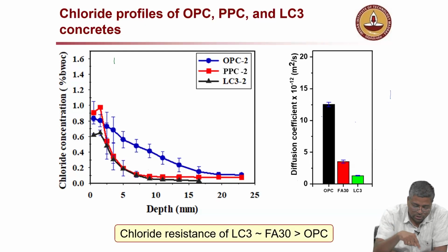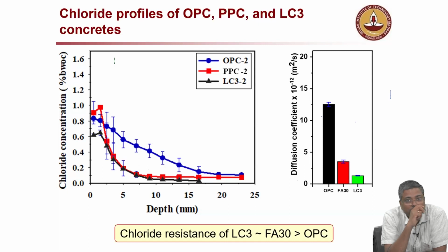Now you can see the slope. Now go through, let's say at 5 mm depth. Which concrete has more chloride in the first graph? Which one has more chloride in the 5 mm depth? OPC. That means what? Speed of penetration is more or less? More. 10 mm, same thing, right? If you look at 10 mm, in the case of PPC, not even a very, very small amount of chloride has reached 10 mm depth.